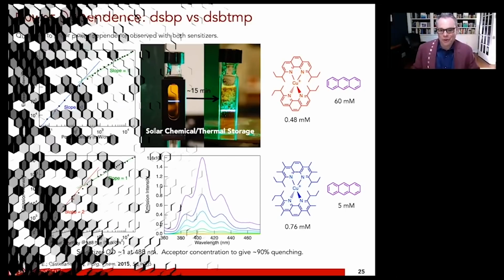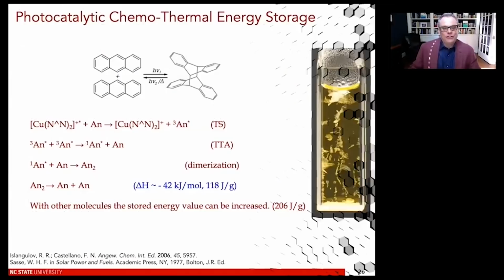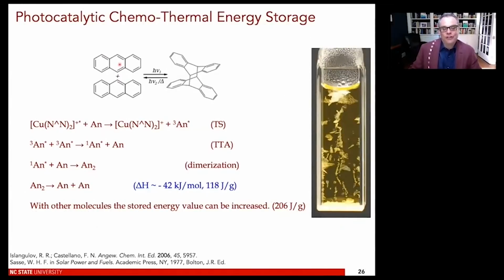So how do we propose to do this? Well, basically the idea is in typical anthracene dimerization, you excite in the UV and you basically get the 4+4 cycloaddition product. But here, the way it's working is we make triplet anthracene sensitized. We get annihilation, which makes singlet anthracene. If you have a high concentration of ground state anthracene, this is the 4+4 reaction. It dimerizes to make this dimer. This dimer precipitates from most solutions because it's very nonpolar.